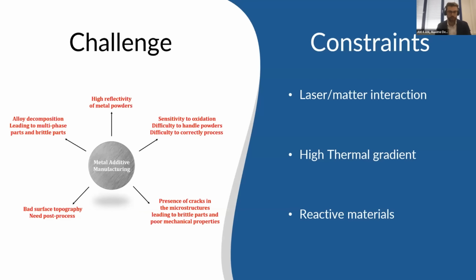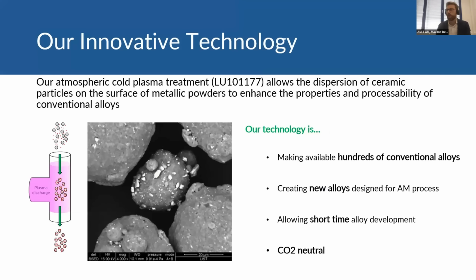So how do we tackle these constraints and this challenge? We developed in 2019 an atmospheric cold plasma treatment, which allowed us to disperse ceramic particles on the surface of metallic powder to enhance the processability and add new properties to conventional alloy. So the idea is a continuous flux process to graft these ceramic particles. And you can see on the micrograph images, all the white dots are grafted particles. So we have a dispersion that is far better than only mixing. This is really the added value.